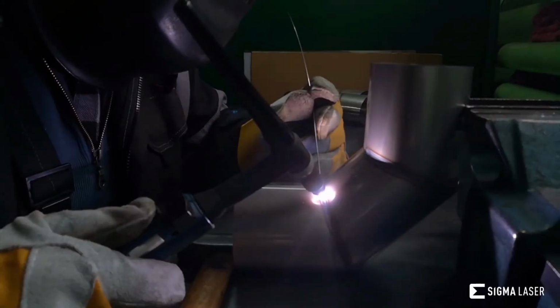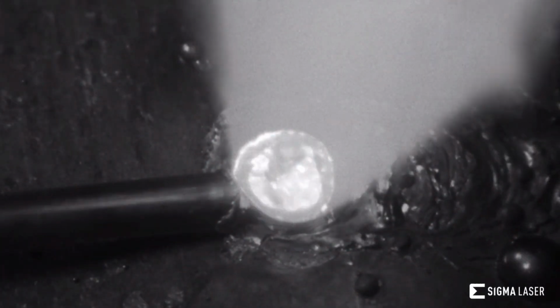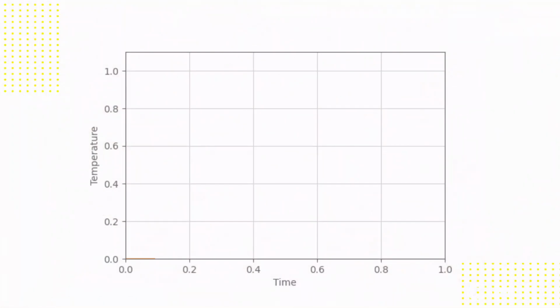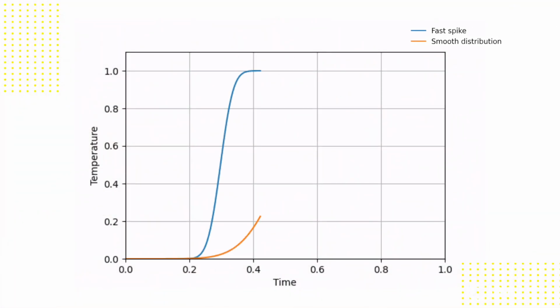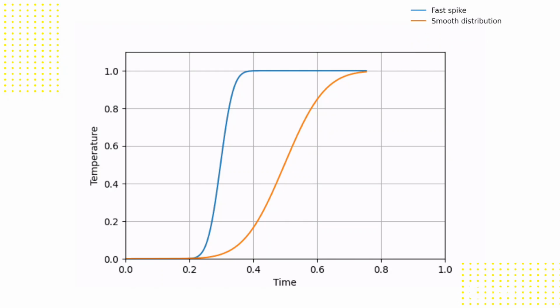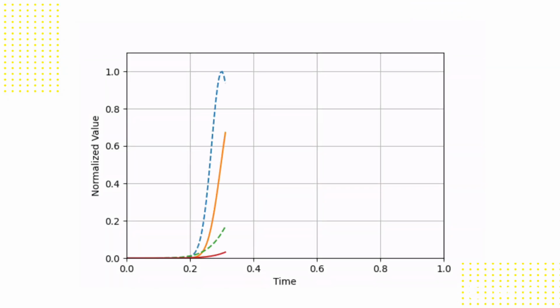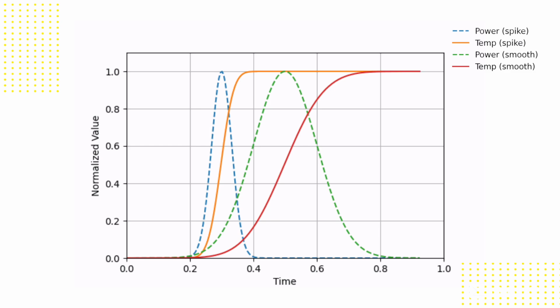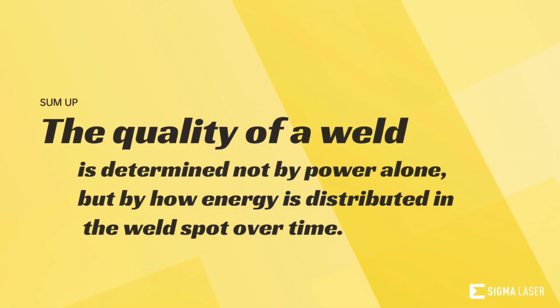In laser welding, everything appears stable from the outside, but inside the weld spot, a highly dynamic thermal process takes place. Within just a few milliseconds, it is decided whether a component will remain structurally reliable, or whether invisible stresses and micro cracks will develop. The decisive factor is the line energy within the weld spot. It determines how temperature evolves during a single pulse. It is not power alone that matters, it is the temporal distribution of energy. The quality of a weld is determined not by power alone, but by how energy is distributed in the weld spot over time.